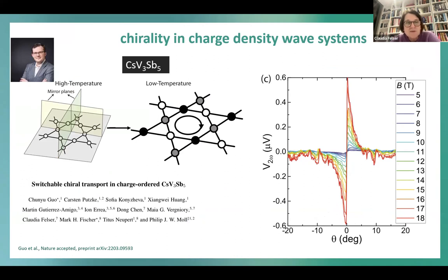And this is only to be mentioned. Just recently, people found that in some very simple systems like tantalum sulfide and so on, you can switch the crystal structure chirality or the charge density wave chirality. And this leads even to very interesting electronic properties like chiral transport. And I'm coming now slowly to the end, don't worry. Which means you can also find materials where you can switch a chirality. And this is really quite new, and also something which I think is super exciting.